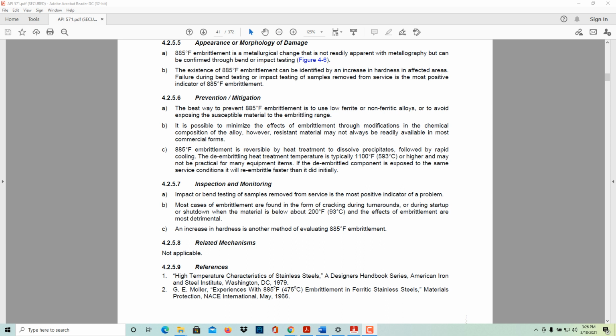Inspection and monitoring. Impact or bend tests of samples removed from service are the most positive indicator of a problem. Most cases of embrittlement are found in the form of cracking during turnarounds or during startup or shutdown, when the material is below 200 F and the effects of embrittlement are most detrimental. An increase in hardness is another method of evaluating 885 embrittlement.